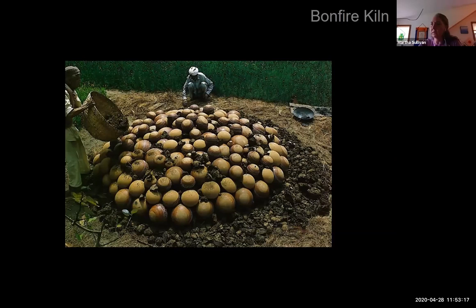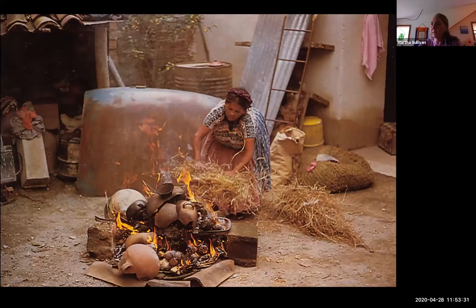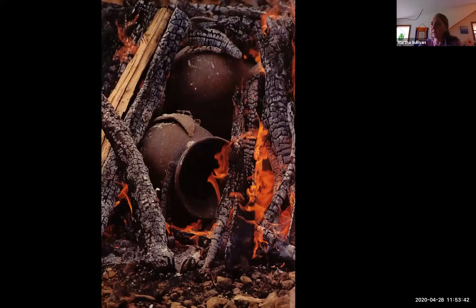These folks are actually putting like probably dung over the top of the pots because it burns super, super hot. And sometimes people will also use like broken pots, old pots, to be an insulator. So you put your good pots in, and then you build your fire, and you put your old pots around it, and then that holds the heat in, and then the pots get even hotter. But you're really looking for the fire itself to come up to maybe like 1,200 to 1,500 degrees Fahrenheit. That's what I've seen read on a pyrometer when you stick it into one of these open air firings. So that's enough to go through quartz inversion. So the material is permanently altered at like 1,100 degrees, but they're probably not so hot that they've been waterproofed in any way.